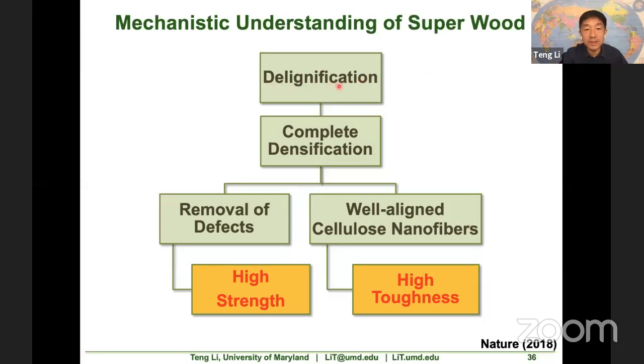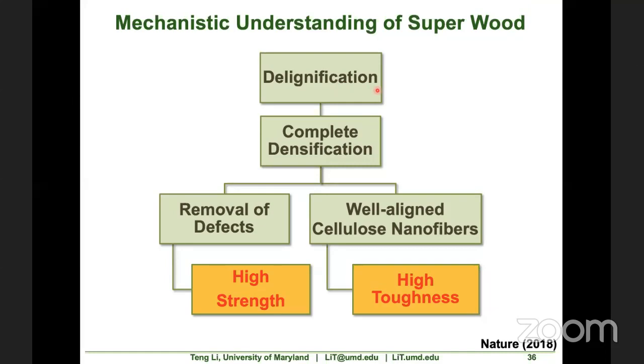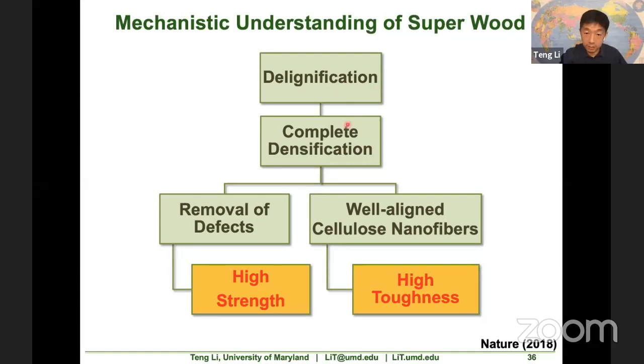So the first step is doing the delignification to allow you to do a complete densification of the natural wood. There were two effects of that. First, the full complete densification removed the defects. Without much of the defect, the strength will be high. And also, with the increased alignment, well-aligned cellulose nanofibers will allow you to have more cellulose interactions among each other and dissipate more energy through the hydrogen bond breaking and reforming. So that will lead to a high toughness.